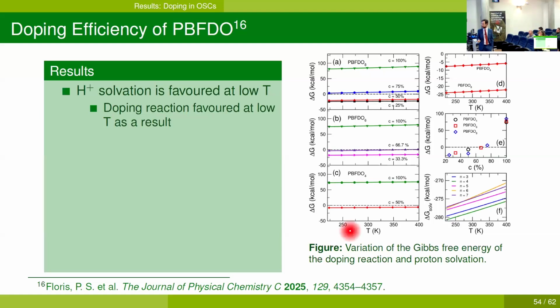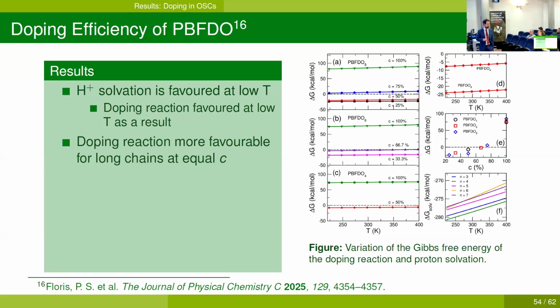So we see that delta G is negative only for doping concentrations lower than 50%. In this case, also for 66% for temperatures lower than 350 Kelvin. And two things to note.